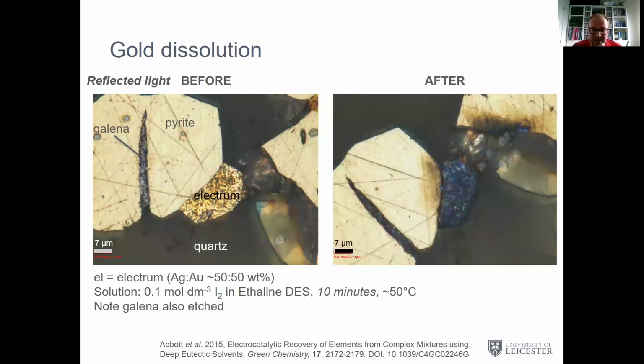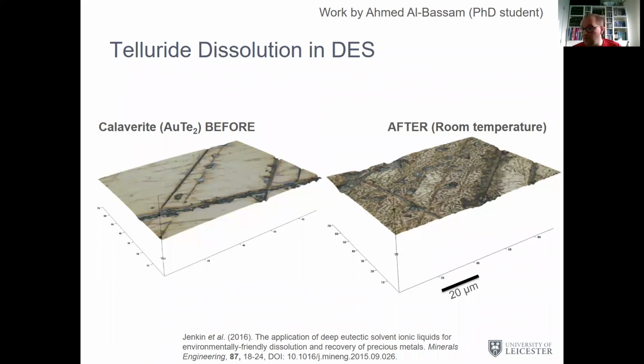And we can see that after 10 minutes, 50 degrees C, so slightly above room temperature in this case, we've selectively dissolved out the gold. So gold solubility is actually faster in these solvents than it is in cyanide. And it's allowing us to target the minerals that we really want, including minerals like gold telluride, calaverite.